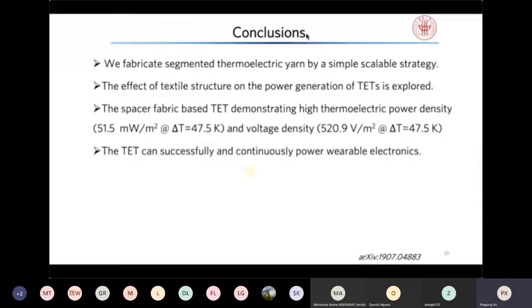All right. So finally, I would like to conclude my presentation. We demonstrate thermoelectric textile, and we investigate the effect of textile structure on the power generation. We also have a high power generation performance with a power density around 50 milliwatts per square meter at a temperature difference around 47 kelvins. And we, for the first time, successfully and continuously power some wearable electronics using thermoelectric textile.